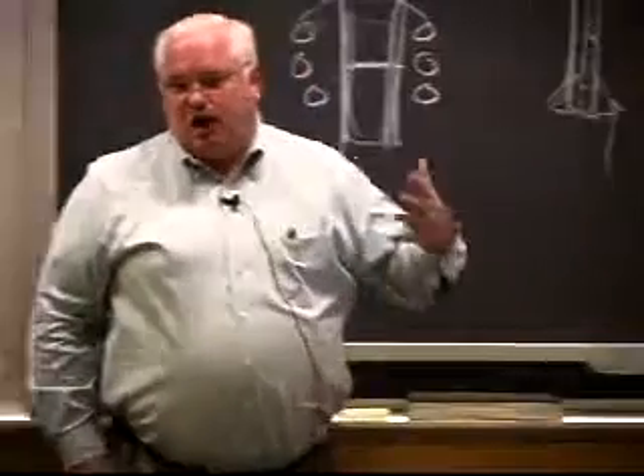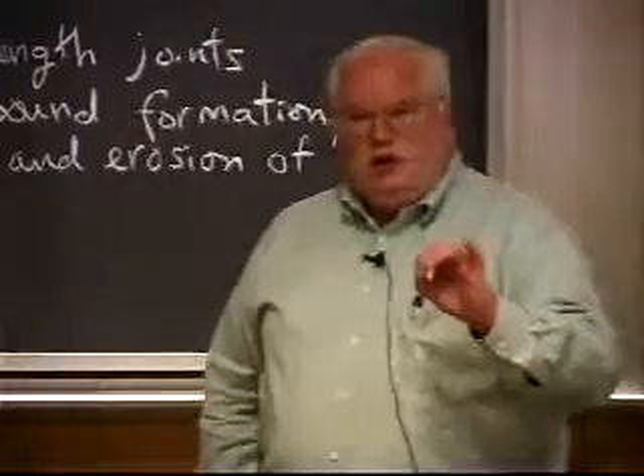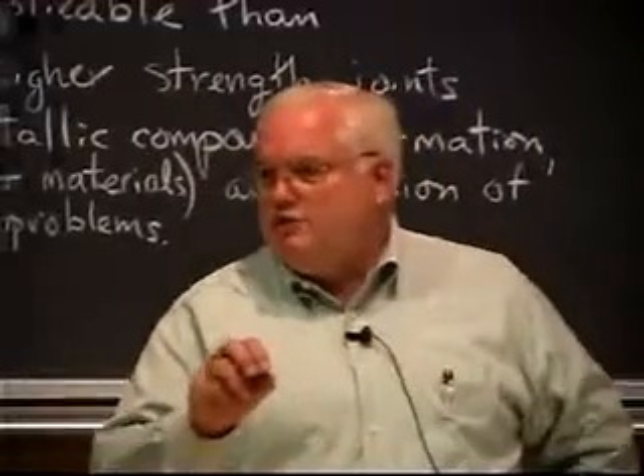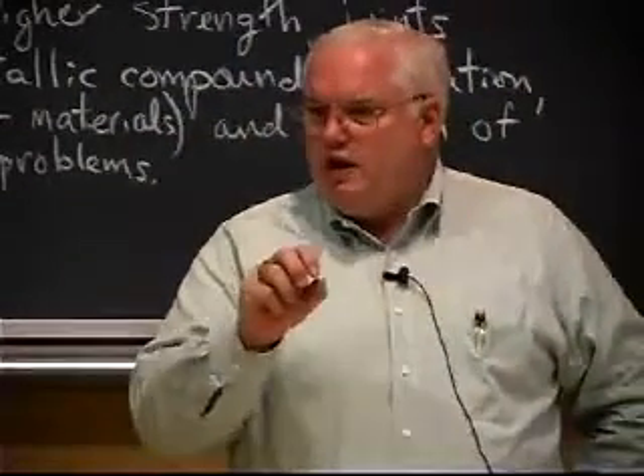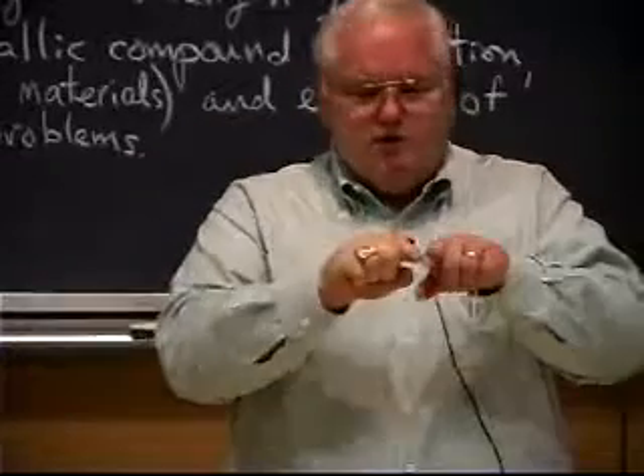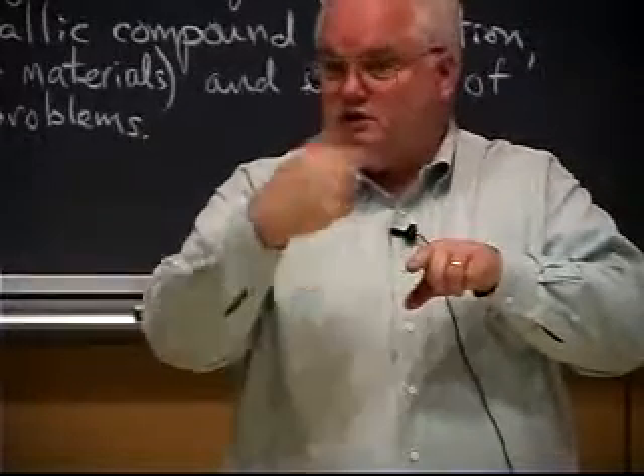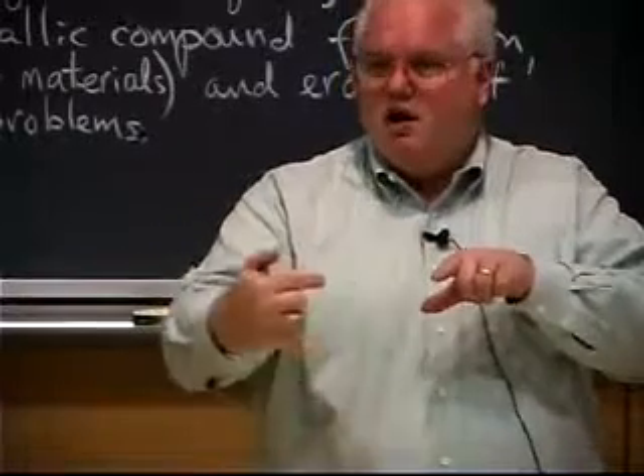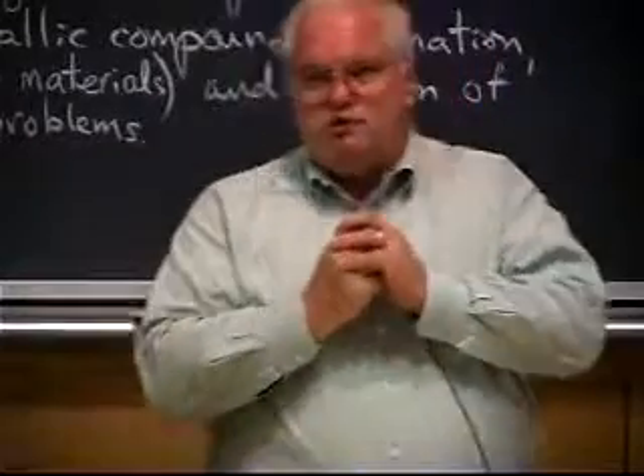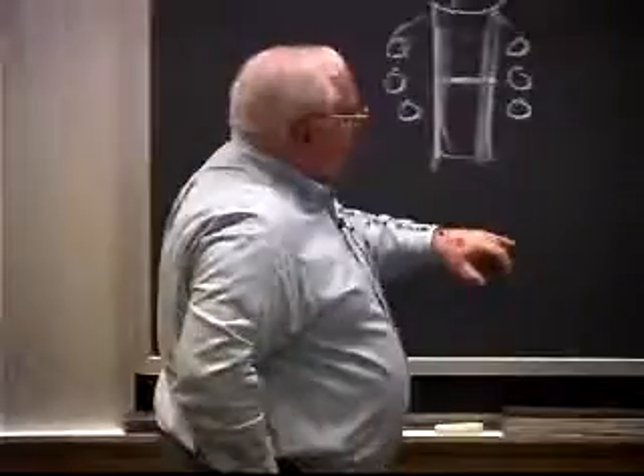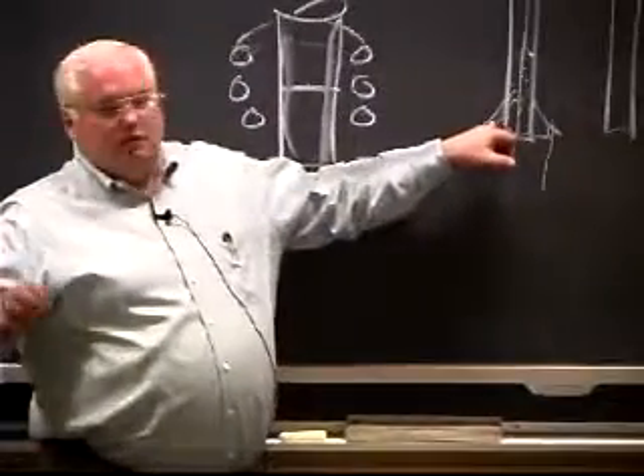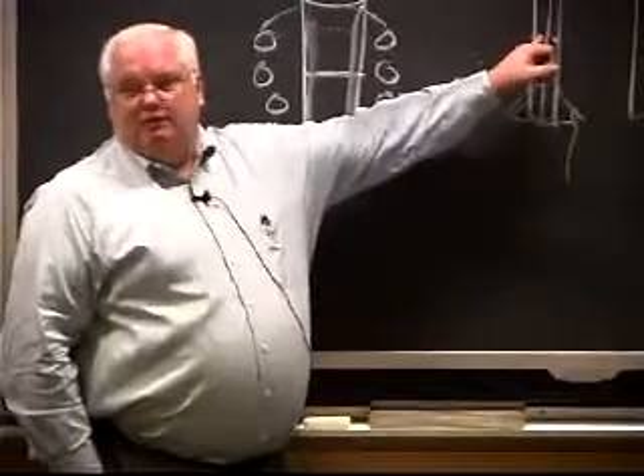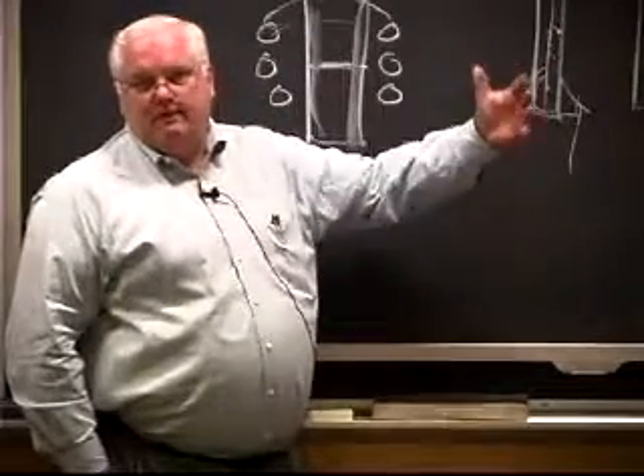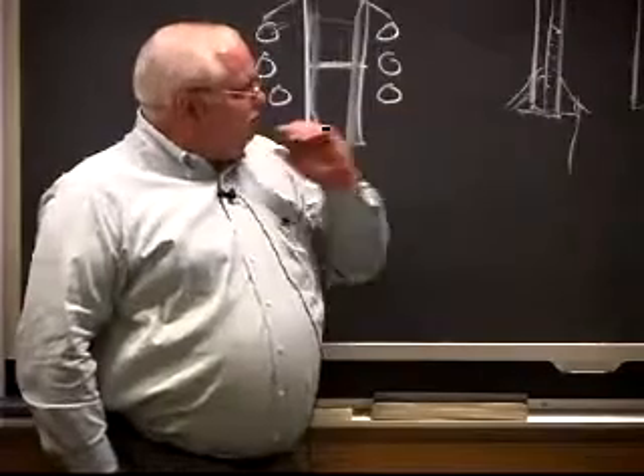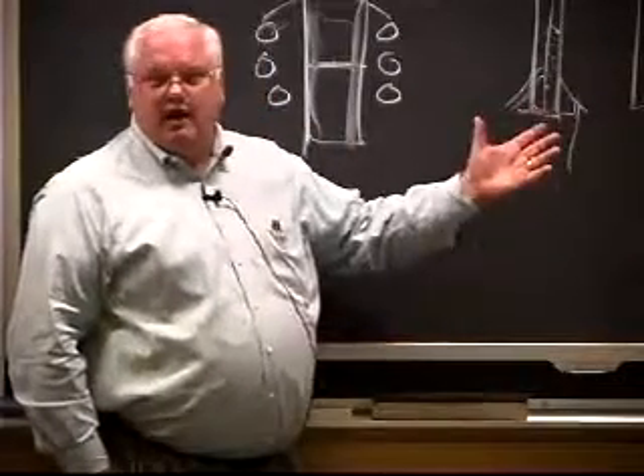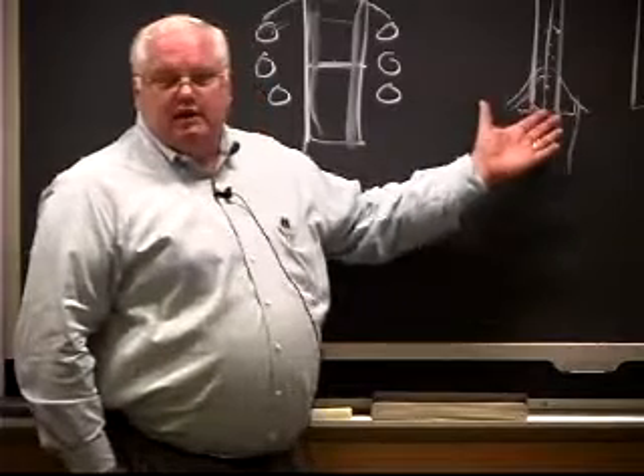Now it turns out in soldering you can buy desoldering tools, which are little wicks, and they're nothing more than a collection of little fibers that have some flux on them, and the solder wants to flow in that, and because of the very small cross-section between the little fibers, the surface tension force, which goes as 1 over R, will suck up into that little fibrous wick, and you'll pull the solder right away from the joint. So if you're trying to desolder a joint, you have these little wicks. Well, we basically had a porous carbon wick for our solder, and the engineer working on it came in and showed me. I thought, oh gee, I should have thought about that ahead of time. I didn't think about it, and he had already figured out the solution.